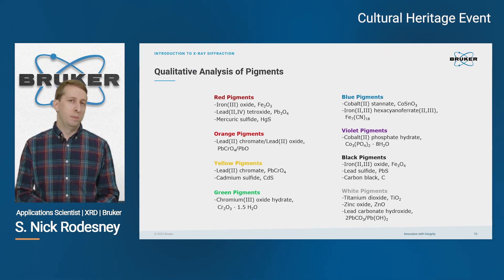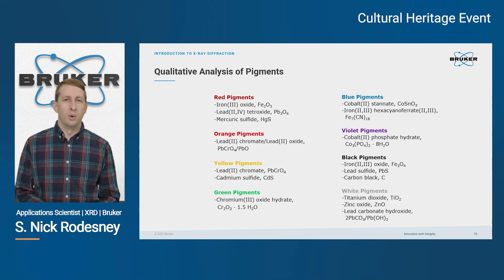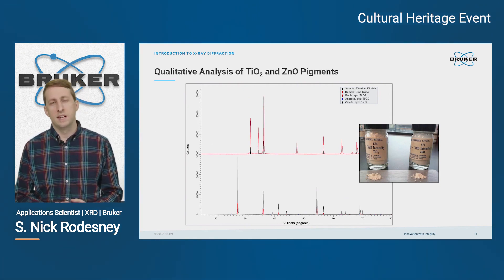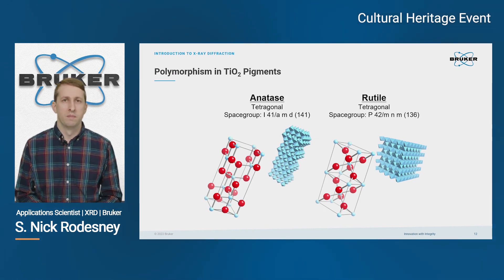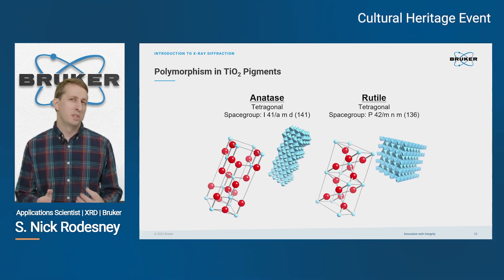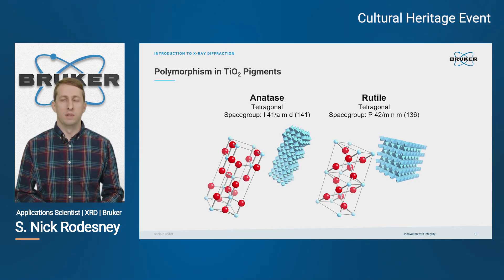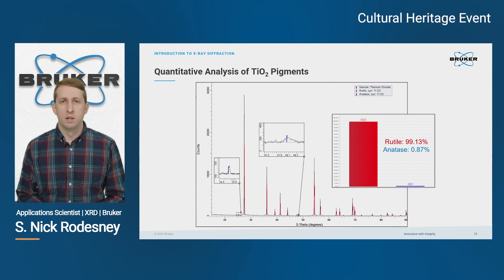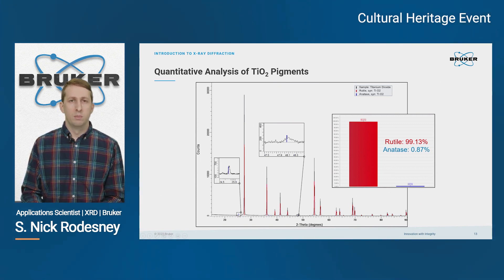You can also look at pigments. This is very important for people looking at art or forensics, where the presence of a particular pigment might indicate authenticity or provenance of a particular object. In this case, we're going to look at a couple of white pigments. Titanium dioxide and zinc oxide are the most common white pigments used nowadays. While you could use an elemental analysis technique to differentiate between the two, only XRD can distinguish between the two titanium dioxide crystal forms. Anatase and Rutile are both common in white pigments, and since they have different crystal structures, that affects other properties like reflectivity and refractive index. This particular white pigment is dominated by Rutile, as seen by the very tall red peaks, with only a little bit of Anatase represented by the very small blue peaks in the background.